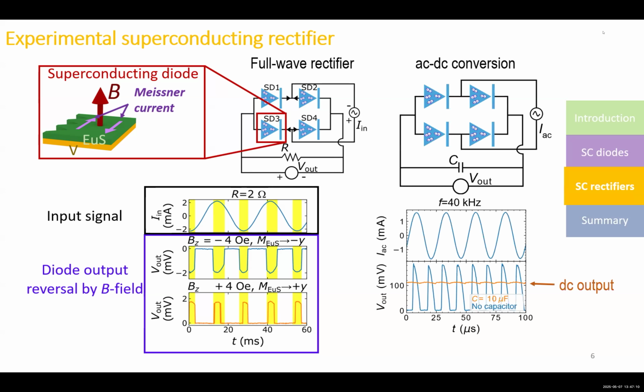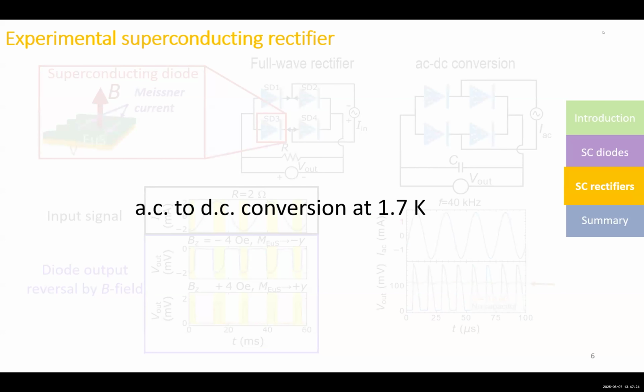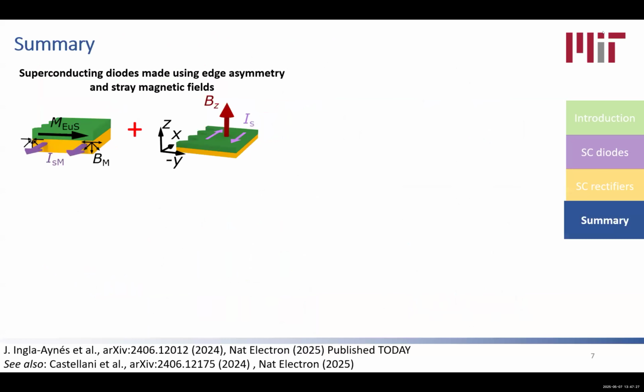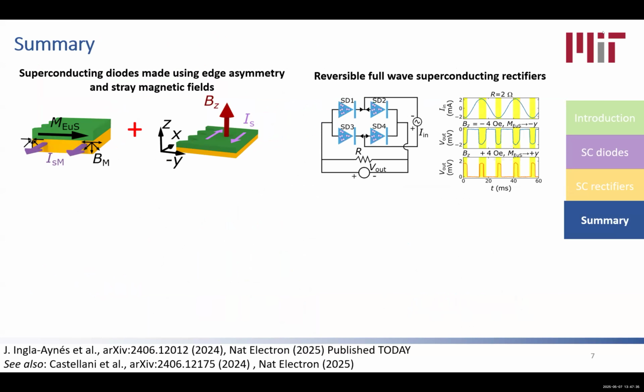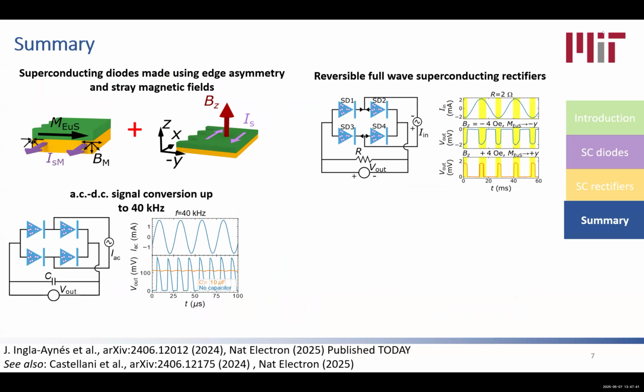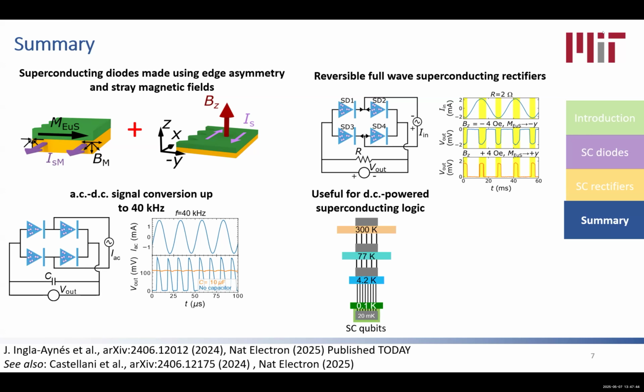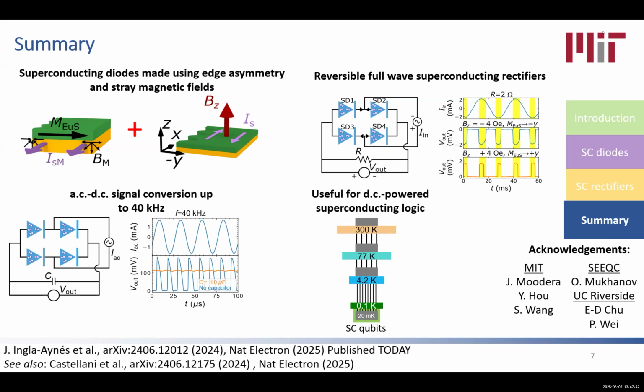And then finally, we just replace the resistor with a smoothing capacitor. And now you have AC to DC conversion, as people do conventionally at room temperature, but now we have done this one at 1.8 Kelvin. And that is the goal that we had here. So sorry, it's 1.7 Kelvin, to be precise. And with that, I hope I have convinced you that by exploiting Meissner currents, you can create what are called superconducting diodes, which are these non-reciprocal superconductors that are useful to, for instance, make full wave rectifiers working at low temperatures that are capable of converting AC currents into DC, and that this is actually useful for superconducting quantum computing. And with that, I thank the collaborators and you all for your attention.